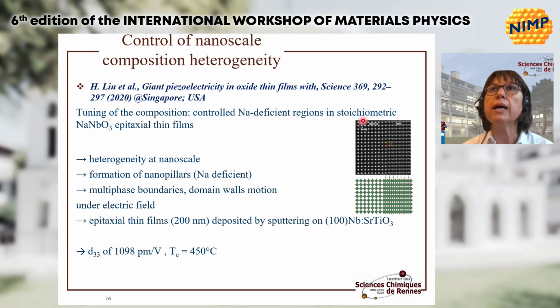That means that the film consists of a matrix of the perovskite with some nanopillars inside that have been grown in the sodium-deficient regions. By the sodium deficiency, some modification in the structure locally at the nanoscales was implied, and by introduction of these nanopillars inside the matrix, some multi-phase boundaries with domain wall motion under electric field have been involved. It's more or less the same approach as with MPBs, but it's different and obtained only with epitaxial thin films, deposited in this case by sputtering on strontium titanate.